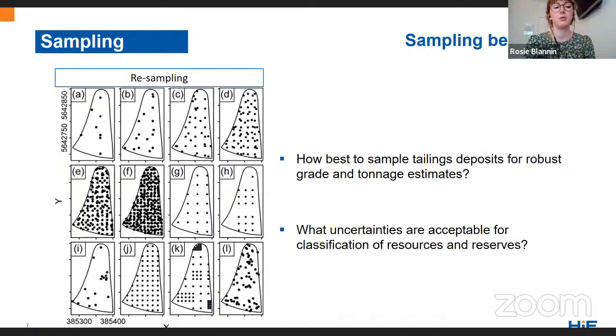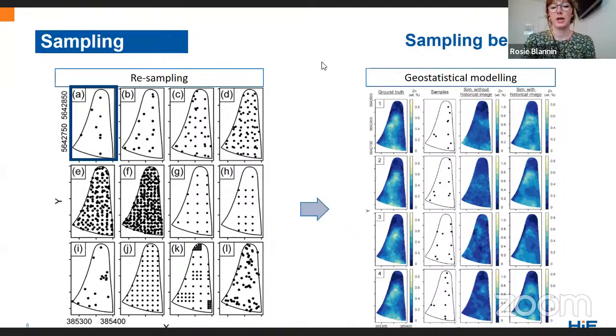A to F are all regular grids with a random point per grid square with a decreasing grid size. G, H, and I are the same number of points as B, but with different configurations. So we have a regular grid and then nested grids and then random points. And J, K, and L are the same as these ones, but with the same number of points as B. So in this way, we could test the sample density required for good estimates, as well as the best configuration of the samples.